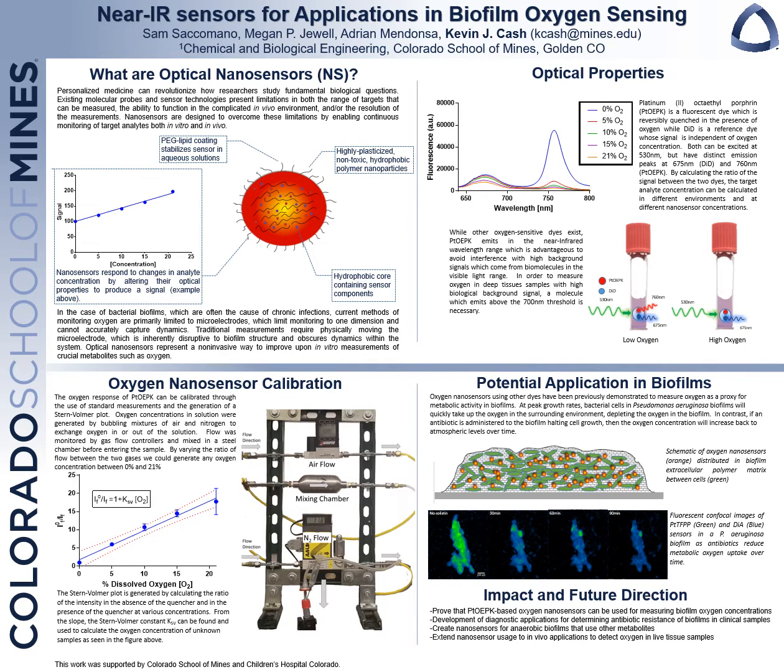We pair this oxygen-sensitive dye with a constant reference dye, DiD, which can be used to normalize the signal intensity to the concentration of nanosensors and the optical properties of the sample environment. These dyes can be excited at the same wavelength, but can be differentiated through an emission spectra captured at different wavelengths.